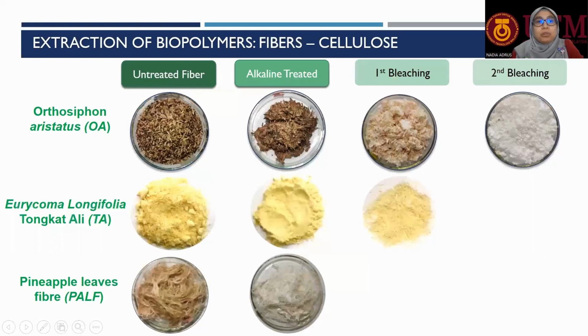Next, I would like to show you the extraction of biopolymers from different resources. The first one is OA, which is Orthosiphon aristatus. Here you see the untreated fiber and the alkaline treated fiber. When you subject the fiber to alkaline treatment, you see that the structure breaks, and the first bleaching gives the removal of lignin. But of course, for the Orthosiphon aristatus plant, it is required to do 2 times bleaching in order to have a fluffier structure like cotton.